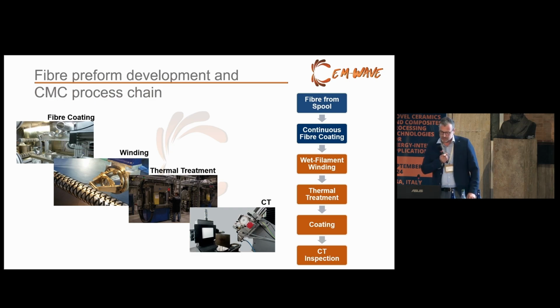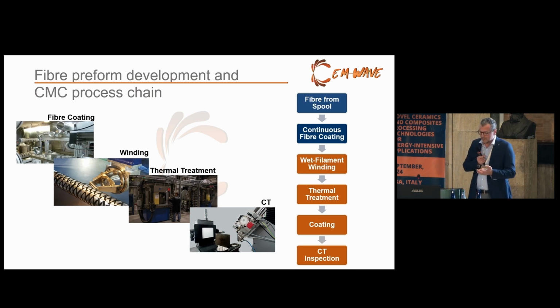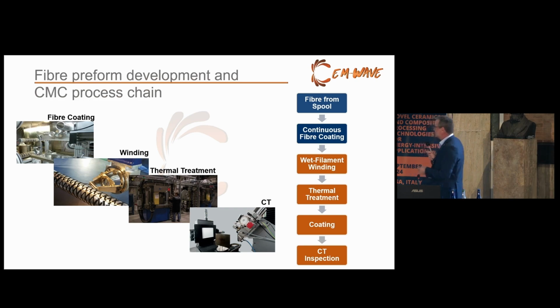But after the fiber coating, we do the wet filament winding. Then, of course, you have the thermal treatment, which is different between the oxide and non-oxide system. On the oxide system, the main high temperature thermal treatment is a sintering, and the main thing using porous silicon carbide fiber preform is a pyrolysis. However, this thermal treatment is followed by the component coating or the preform coating, let's say, which is again important in the large scale to cover your material.